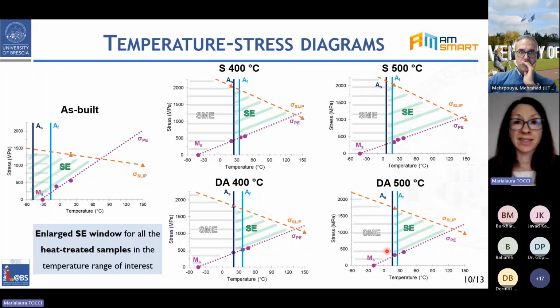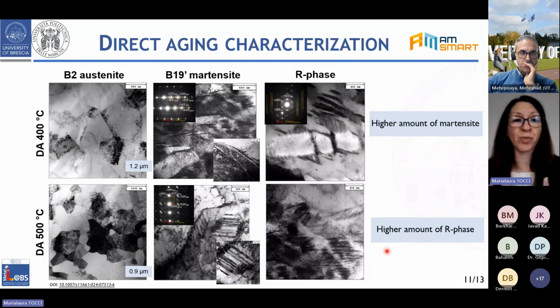To better understand the reason for this material response to the heat treatment, we more deeply characterized the microstructure. So we performed TEM analysis. We preferred to carry out this investigation on the two conditions that for us are more relevant, so the two direct aged conditions, the one at 400 and the one at 500 degrees Celsius.